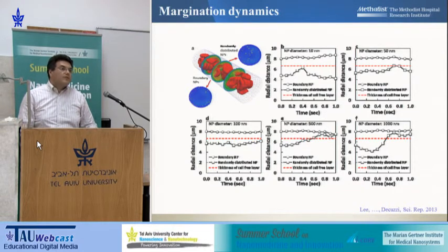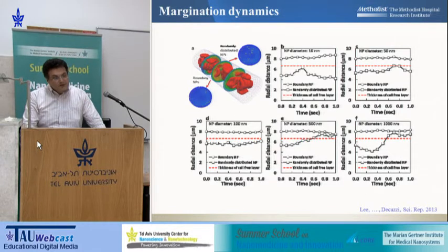So we need to have nanoparticles that are able to navigate the vasculature in close proximity of the vessel walls. And this is the reason why we're working with micron size and sub-micron nanoparticles. We're not working with 100 nanometers, 200 nanometers nanoparticles. The discoidal particles that I've shown you, both the polymeric as well as the mesoporous silicon particles, they are 1000